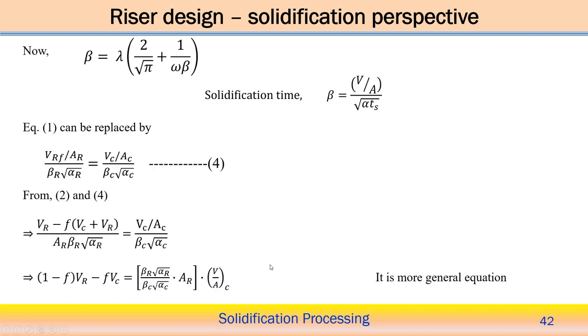Now if we want to take care of the curvature effect during the solidification, we define a non-dimensional parameter beta. I think we have discussed it already in the previous class, in the same module. So here beta equals lambda into 2 by root pi plus 1 by omega into beta. Omega is the factor here. Beta is the non-dimensional parameter with which we can take care of the curvature effect. So this is the expression for beta. Now for the solidification time we also define the V by A ratio divided by the square root of alpha TS. This is the non-dimensional parameter we have already discussed in the previous class.